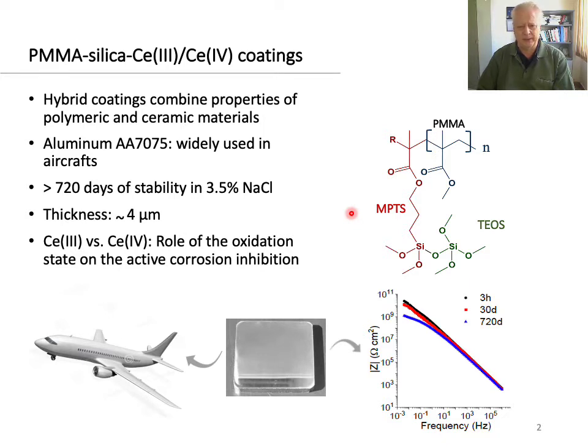This material can be applied as a very efficient anti-corrosive barrier to protect metallic components such as aluminum 7075 alloy, preferentially in the aircraft structures. To ensure a long-term protection for this coating system, two conditions have to be fulfilled: to provide an effective physical barrier against aggressive agents with an active protection by the self-healing ability. Now our results show that only 4 micrometer thick PMMA silica coating provides effective corrosion protection for more than 720 days in contact with standard saline solution.